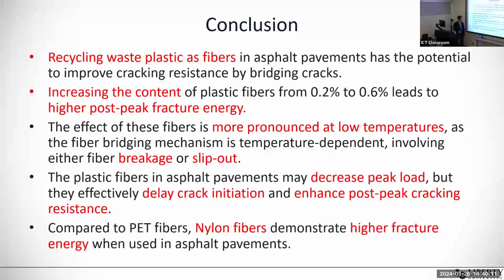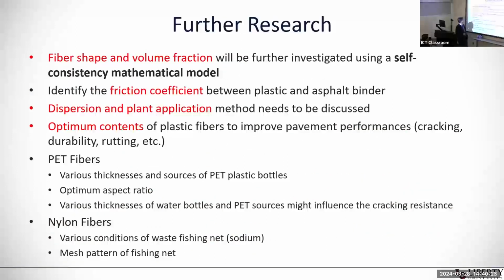Compared to the PET fiber, nylon fibers show higher fracture energy when used in asphalt pavements, but so far we use only one content and one type of nylon. What we are going to do is look at different sources of fishing net. We used a brand new fishing net, which costs about $20 on Amazon, and we chopped it. So this is a new nylon.